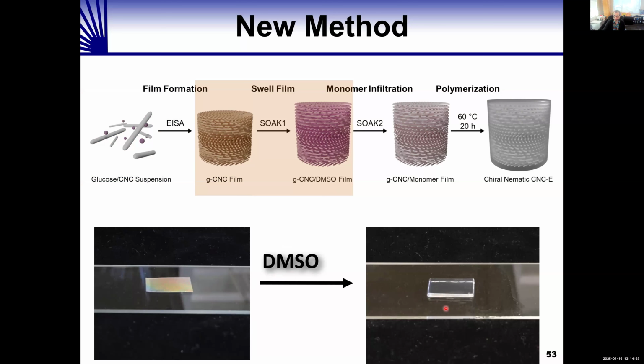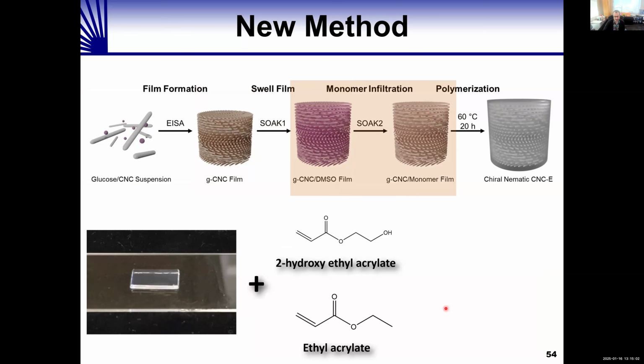Now what we can do is we can take this swollen film and we can immerse it in a mixture of monomers. We spent a long time optimizing this, and what we found works well is a mixture of 2-hydroxyethyl acrylate and ethyl acrylate. These are commercially available monomers. We can buy them by the bucket load. We swell it with those.